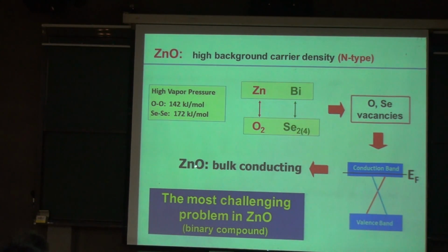That makes the material you prepared a conductor. So the Fermi energy is located in the conduction band. For you to make the intrinsic zinc oxide semiconductor, you need something to reduce the density of the vacancy. I think Professor Feng also did a lot of this kind of thing. Many people work on the mechanism of this vacancy or the defect origin in the zinc oxide, but still not the mass development. So this is very similar.